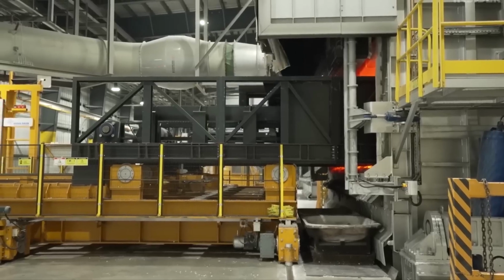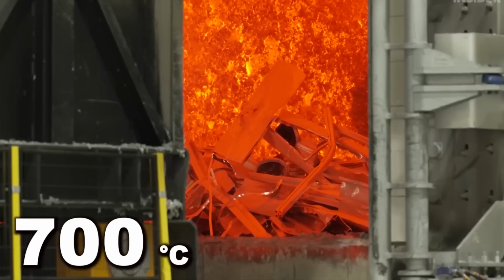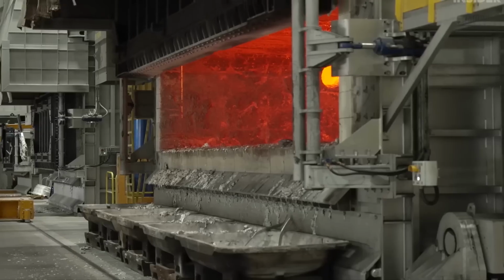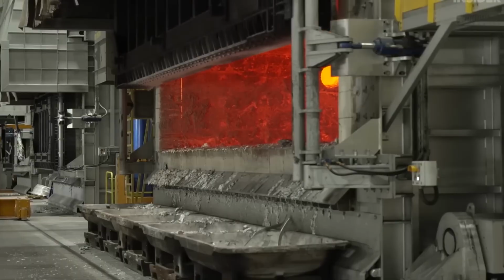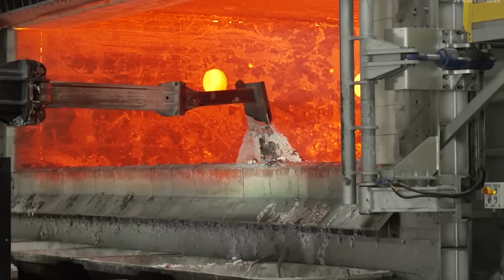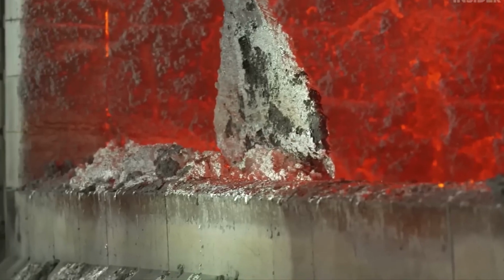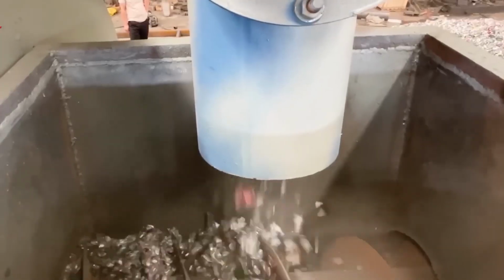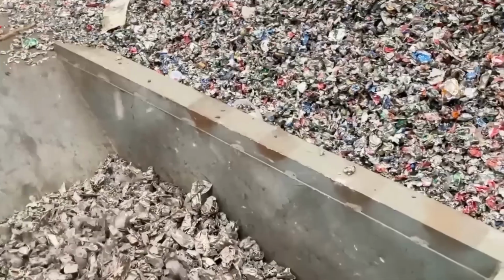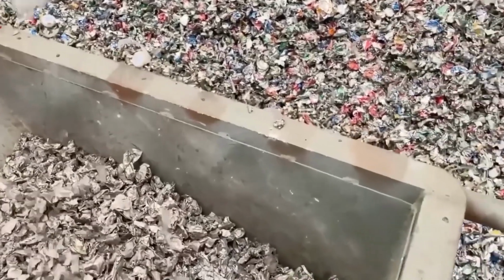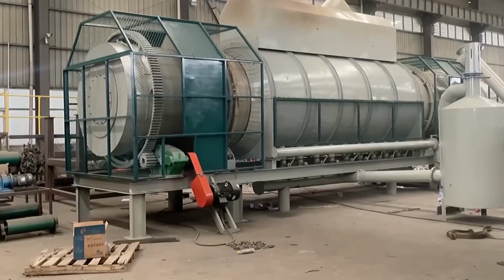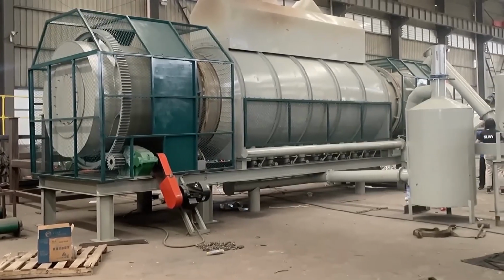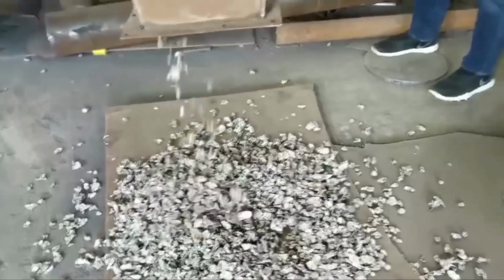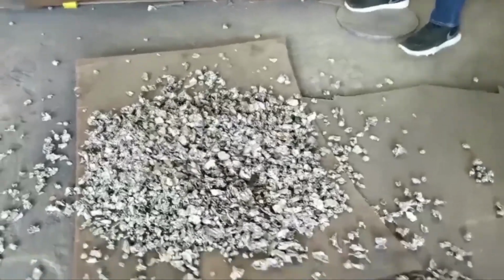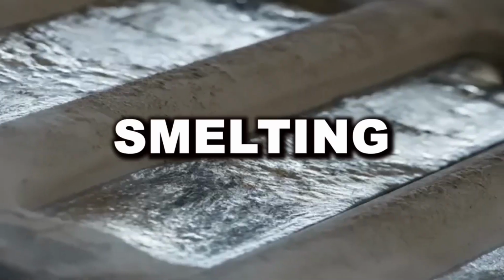Inside the furnaces, the temperature soars past 700 degrees Celsius, hot enough to vaporize the coatings instantly. As the aluminum shreds pass through the fiery environment, you can almost imagine the heat radiating off the walls. The paint and lacquer are reduced to vapor within seconds, leaving clean, bare metal behind. Airflow within the furnace carries away the vapor to ensure it doesn't settle back on the aluminum. This step is critical because even a small amount of leftover residue could cause imperfections in the next stage, smelting.